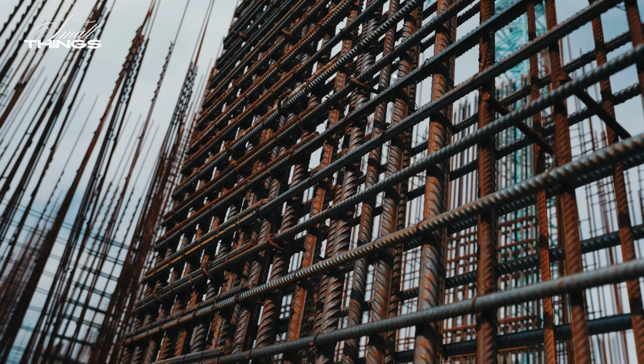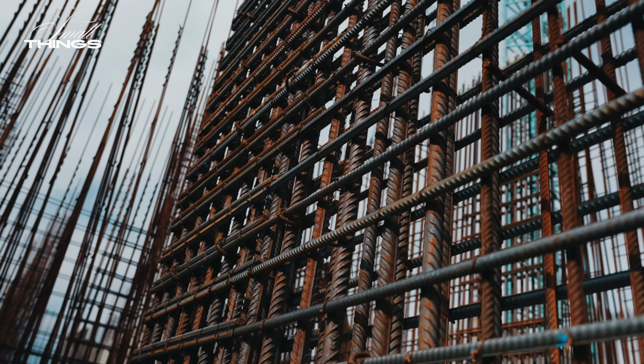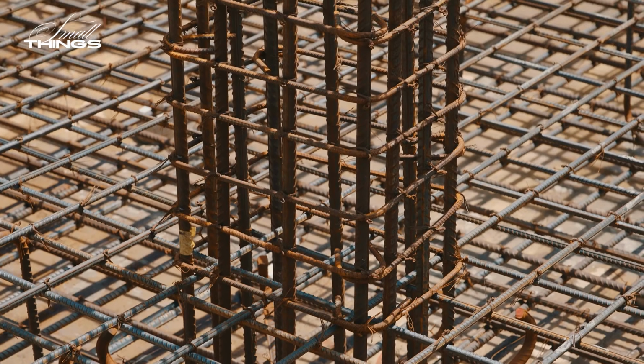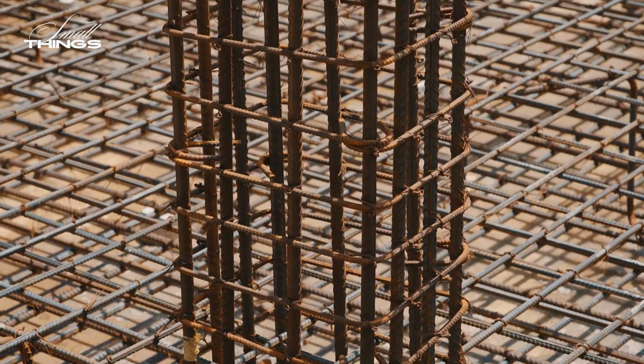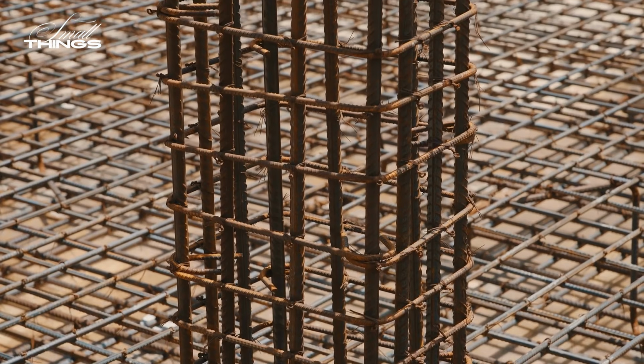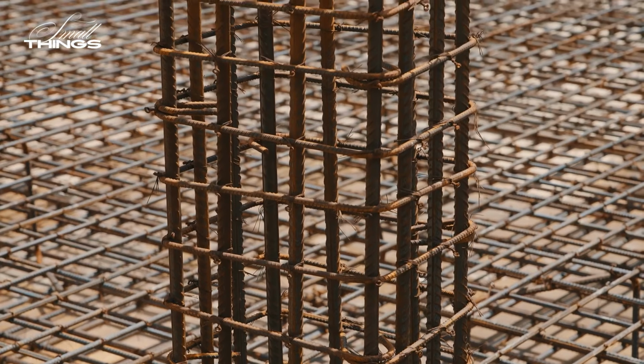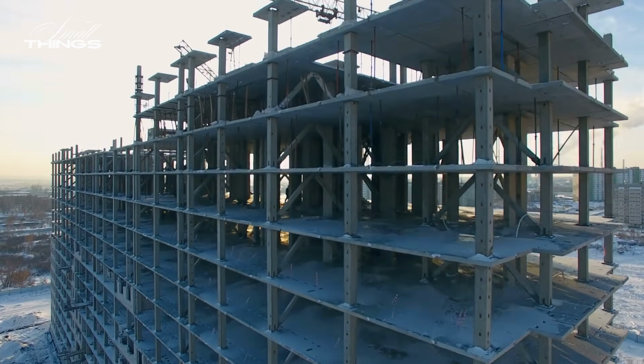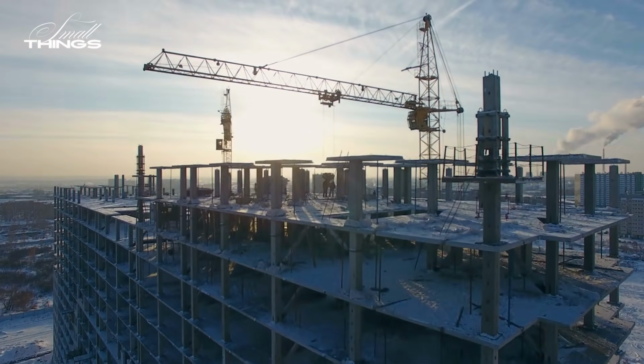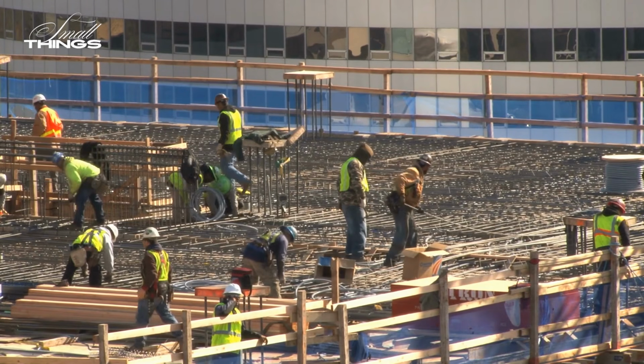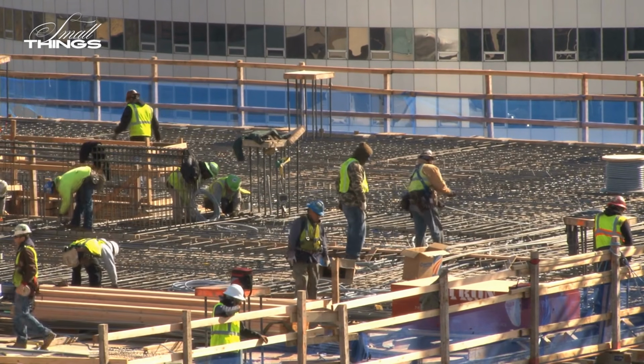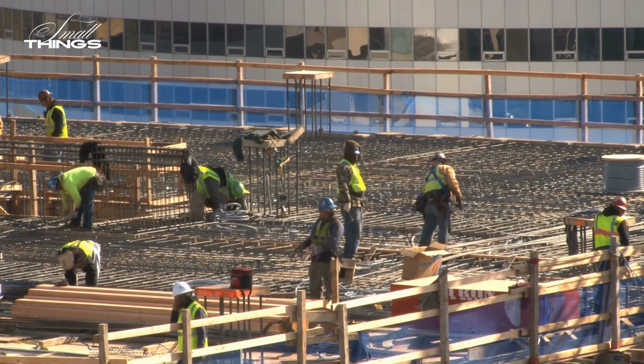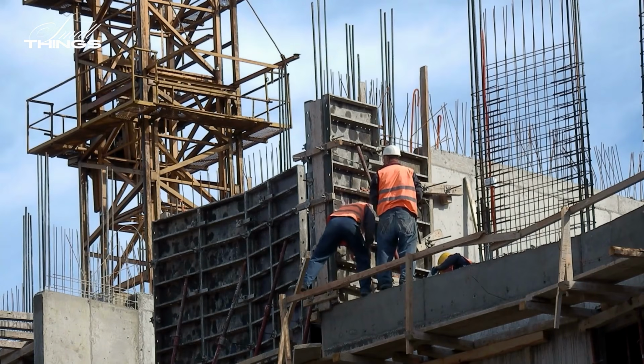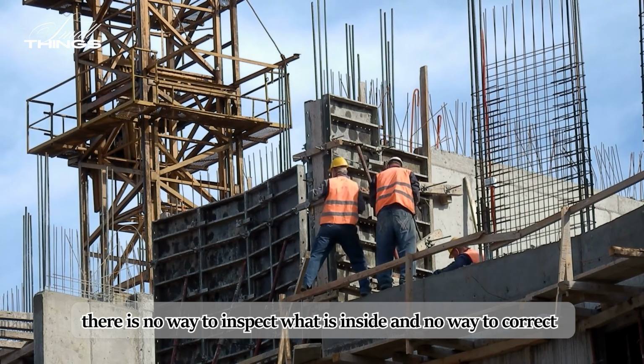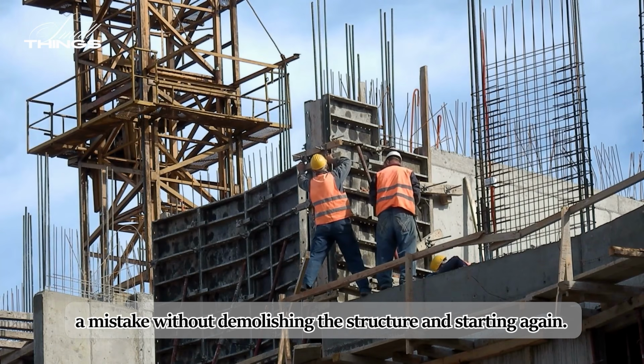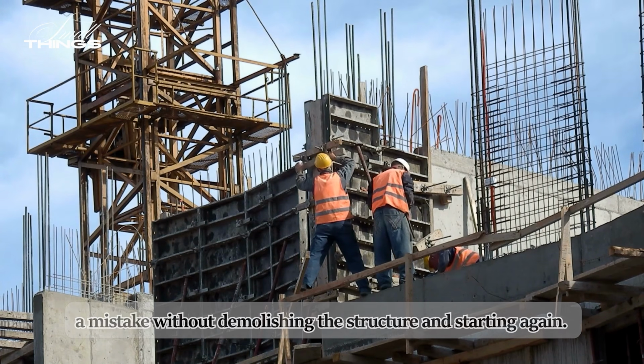A bar placed where only compression exists contributes nothing to tensile capacity. Worse, steel placed incorrectly can interrupt the natural load path through the concrete, creating stress concentrations where none would otherwise exist. The structure can end up weaker than it would have been without the rebar at all. Quality control at the construction site includes checking that the rebar cage matches the engineer's drawings before concrete is poured, because once the concrete sets, there is no way to inspect what is inside and no way to correct a mistake without demolishing the structure and starting again.